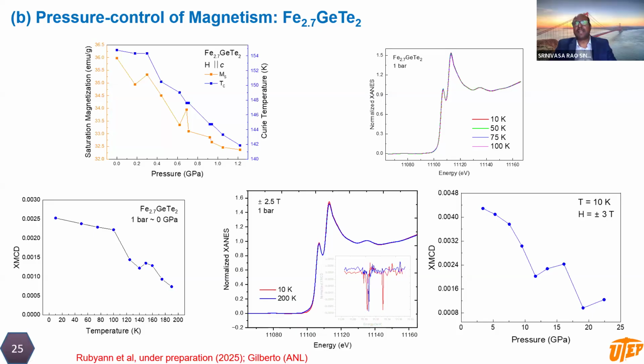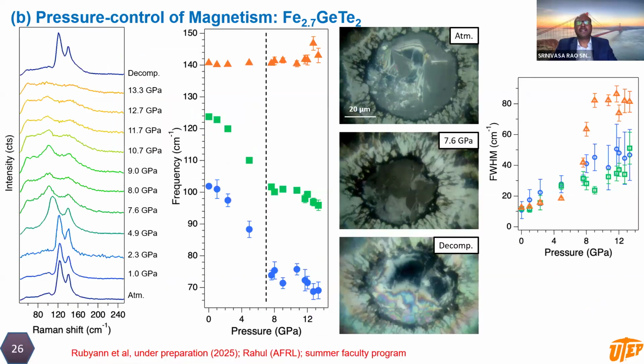To complement these findings, at the Air Force Lab, as a part of our summer faculty program, myself and my students spent one summer month there, and we conducted Raman measurements as a function of pressure. As you can see, at atmospheric pressure it's a beautiful Raman spectrum. As you start applying pressure, you see that the Raman signals disappear, and they disappear completely at about 13 gigapascal.